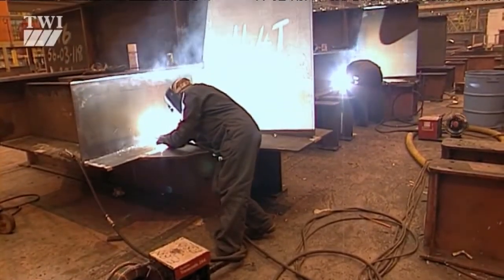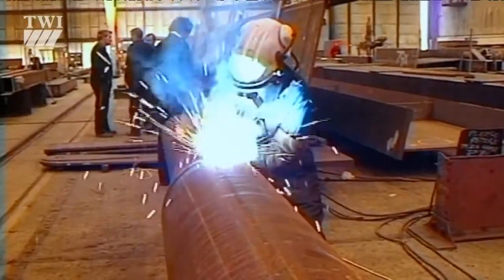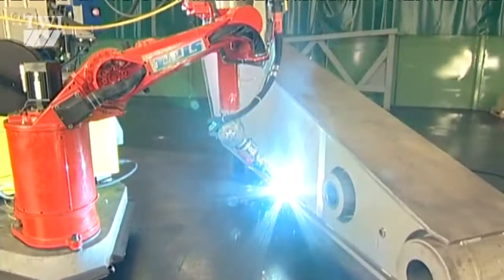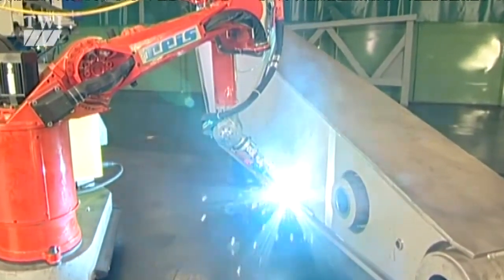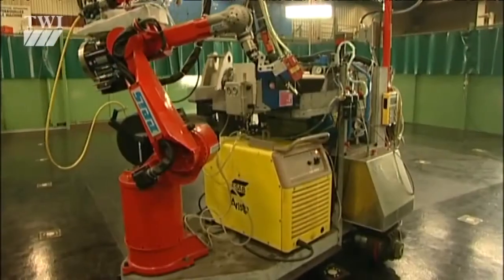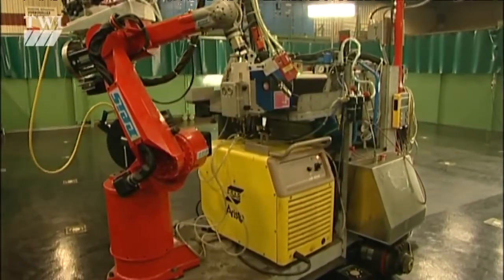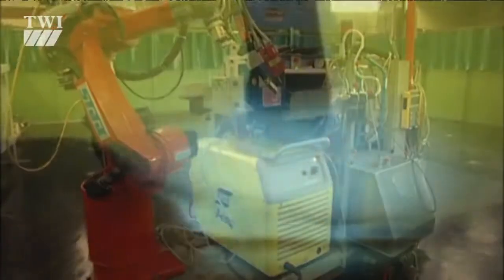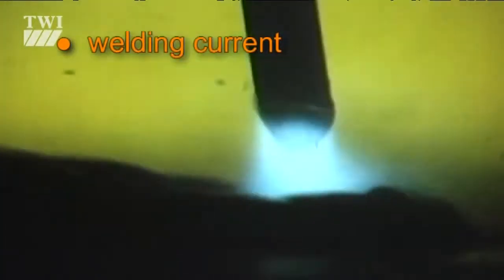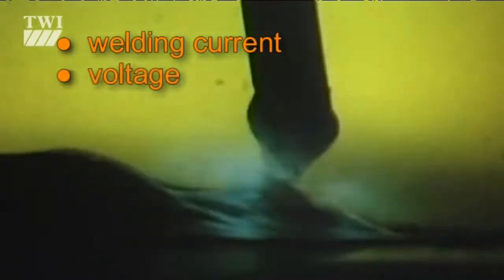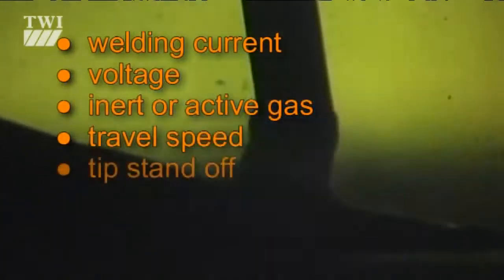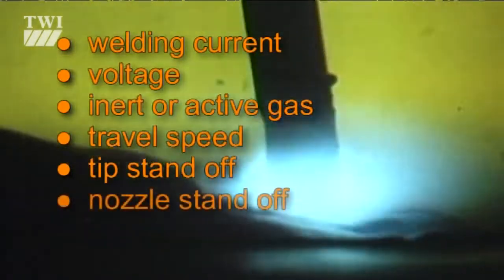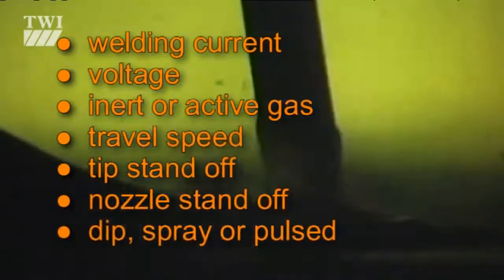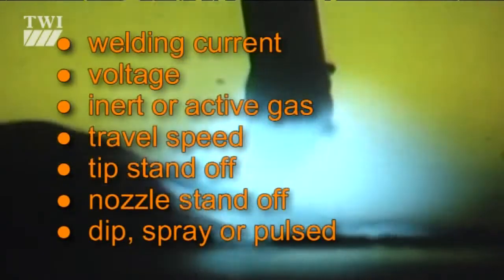So the process offers high productivity, whether it's operated manually or in a mechanized way, such as by robot. In mechanized welding, all parameters are under automatic control, but they can be varied manually during welding. So the variables are welding current, which is proportional to wire feed speed, voltage, the choice of inert or active gases, the travel speed, the tip standoff distance, the nozzle standoff, and the type of metal transfer: dip, spray, or pulsed.